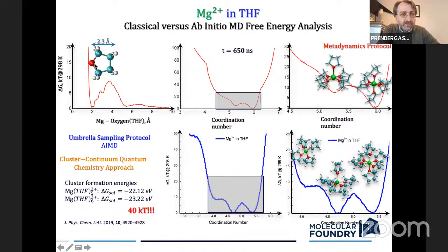So we imagine the situation where we have the free energy difference of association between magnesium and the oxygen of the THF molecule as a function of that bond length. As we separate one THF from the magnesium, you should return to 0 free energy difference, because as you remove one molecule, it will be replaced by another from the solution. So the net difference should be 0 as you go to long distances. That's a good check that we're doing the dynamics in the right way.